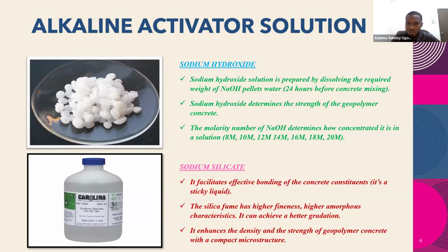Normally, we have from 6 mole to 20 mole. A 1 molar solution is prepared by dissolving 40 grams of these pellets into 1 liter of water. That is how you calculate the molarity. Now, when you dissolve it, it releases a lot of heat. The solution becomes very, very hot, and it can even damage your hand or the skin. So most times when you want to cast, you prepare your sodium hydroxide 24 hours prior to your casting to enable it to cool down and enable you to cast your concrete.